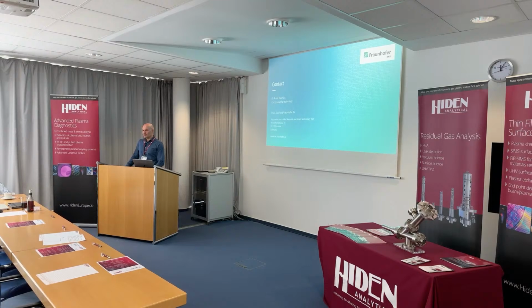And we did EDX measurements of it. It's working okay, even at that low level for EDX measurement. Usually for low atomic percent, it's getting more difficult, of course. We also did, or not we, another Fraunhofer Institute in a project did XPS measurements of it, with some sputter depth scan, seeing the distribution of the single elements within the coating depth. And so we see that we do not have the highest amount of molybdenum on the surface. It's 20, 30 nanometers below the surface. We did even a rather complex scattering, and so it's there without doubt.